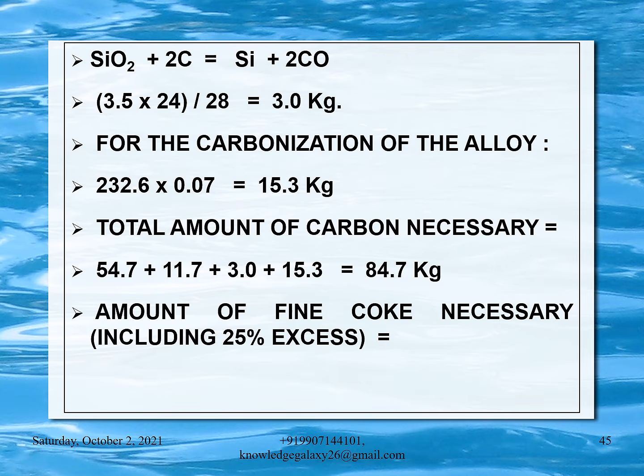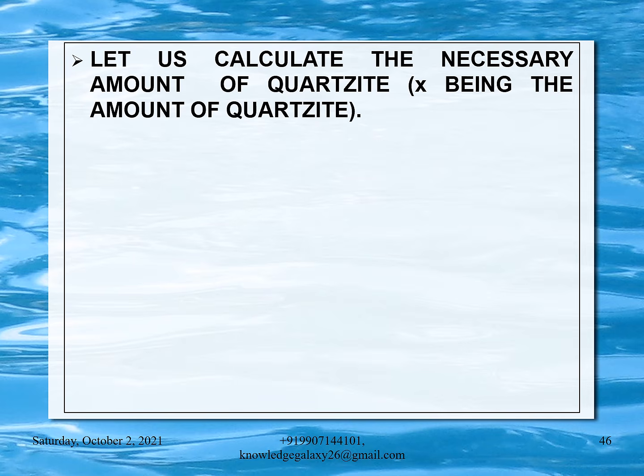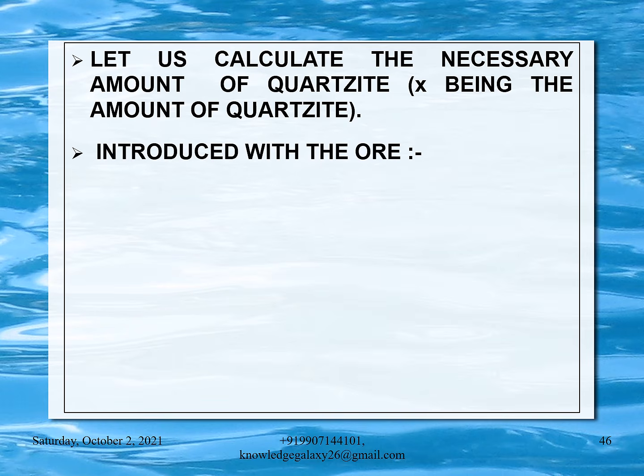Amount of fine coke necessary including 25% excess is equal to 84.7 into 1.25 divided by 0.87 is equal to 121.7 kg. Here 0.87 is 87% of fixed carbon in the fine coke. My dear friends, you have to always keep in mind the various contents of the percentages of the particular element, from where it is getting, and its atomic weight and its recovery in the metal and slag separately. Let us now calculate the necessary amount of quartzite, X being the amount of quartzite introduced with the ore.